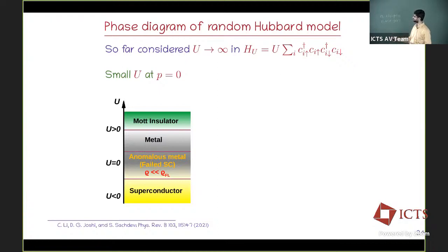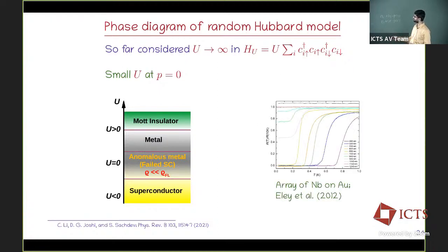It also has some interesting properties. This work was essentially motivated by a set of experiments that people had reported in two-dimensional disordered superconductors, where you have a clear superconducting transition, but then for certain tuning parameters, it can be magnetic field or interactions or some gate voltage, the resistivity saturates at some small value. I think some of the curves are not absolutely visible, but there is a resistivity saturation at some slightly lower values, much lower compared to the metallic or Fermi liquid value. And what controls this residual value?